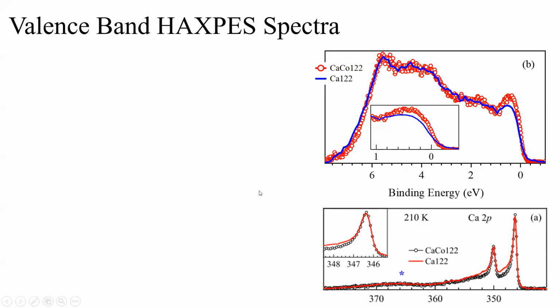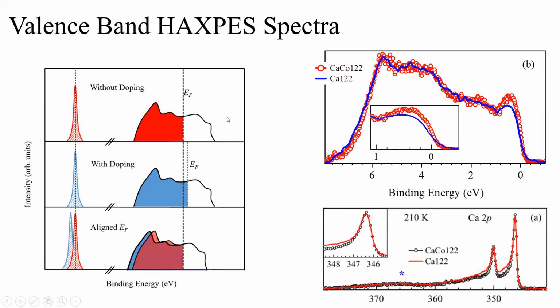Now, what do we expect from the electron doping? If I take this as the compound without doping, you will have a Fermi edge, and this is the core level, this is the valence band, and there is a Fermi edge. So states below this are filled. Now, if you dope electrons, you will fill the allowed, unoccupied states above the Fermi energy. So now you will have a new Fermi energy, which will lie somewhere here.